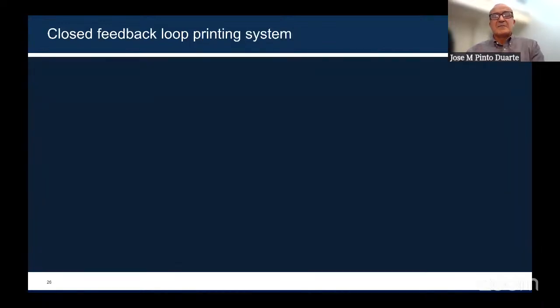And then another aspect is a closed feedback loop. So what happens when you are printing? We need at least 3 people. One is controlling the robot, one is controlling the extruder, and another one is overseeing the operations. So you need to keep an eye on how things are going, like if the material becomes too wet or if it becomes too dry. So you need to adjust the settings in real time. For instance, you need to increase or decrease the amount of water, or you need to increase or decrease the pump speed or the robotic arm speed.